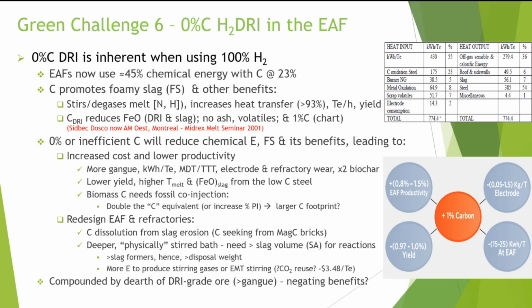The chart on the bottom right is something that our friends at ArcelorMittal put together for the benefit of carbon in their DRI. And they said for every 1% of carbon that they had in the DRI, they reduced their kilowatt hours in the furnace by 25 max. Electrodes are down 1.5 kilograms. The production can be up as high as 1.5% increase, and the yield is up to 1%.